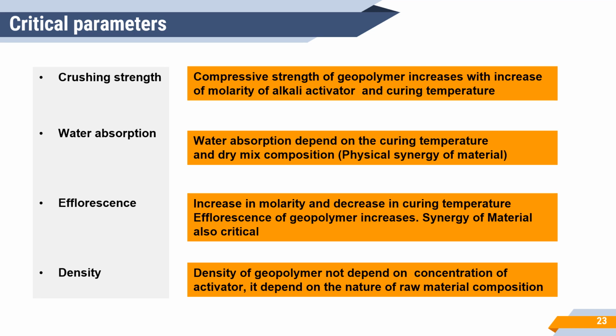When we make geopolymer for construction and building applications, the following parameters are decisive and related to the material properties. Crushing or compressive strength of geopolymer is directly proportional to alkali activator concentration and curing temperature. Water absorption depends on the curing temperature and dry mix composition. The physical synergy of material has a direct impact on water absorption. With increase in molarity and decrease in curing temperature, efflorescence of geopolymer increases. Density of geopolymer does not depend on the concentration of activator. It mostly depends on the nature of raw material composition.